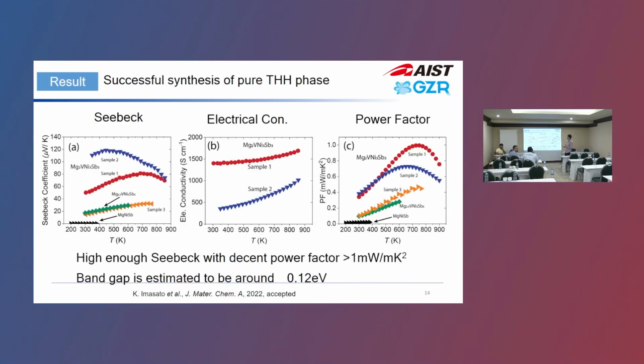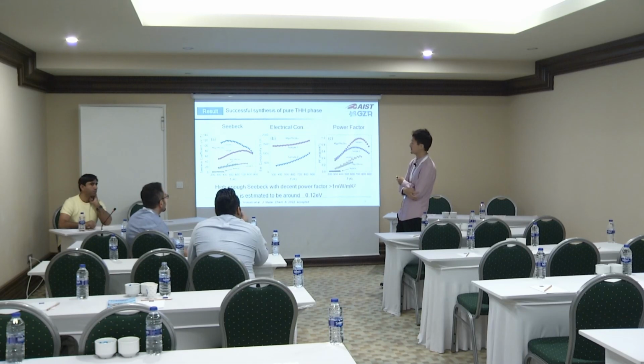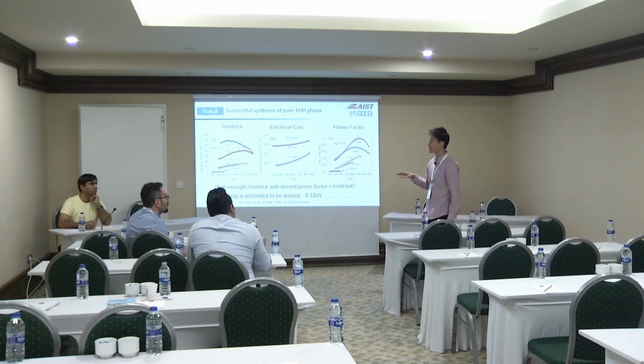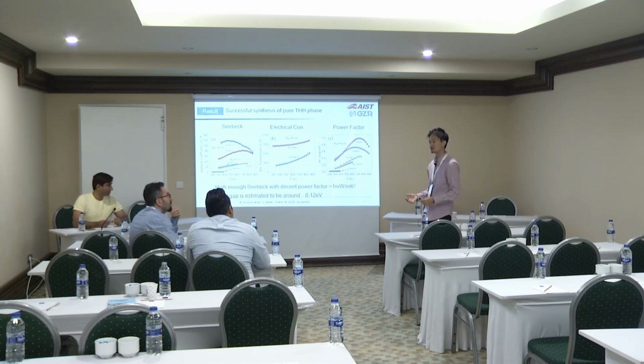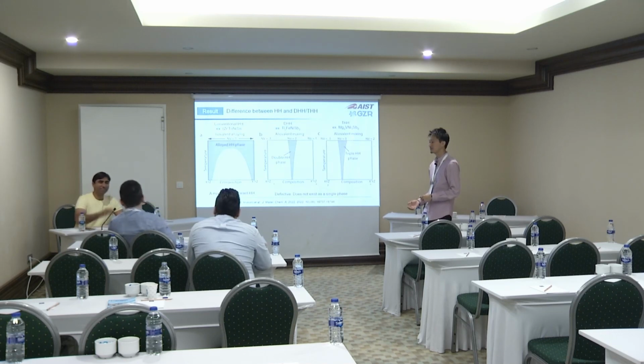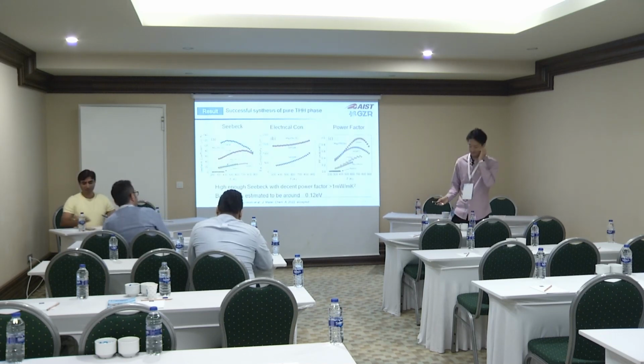Yeah, that's interesting, because the Seebeck coefficient is quite high. That shows that holes most likely dominate. So the P-type should dominate in this Half-Heusler, or should the most favorable mixture have a higher content of the P-type, or no? I'm not sure. It's kind of difficult to control the exact amount of magnesium, so maybe it affects it somehow. But we are actually trying to balance this by changing the ratio, to see whether we can get to N-type or not. The N transition might be interesting to see. Okay, thank you very much, Kazu, again for this nice talk.